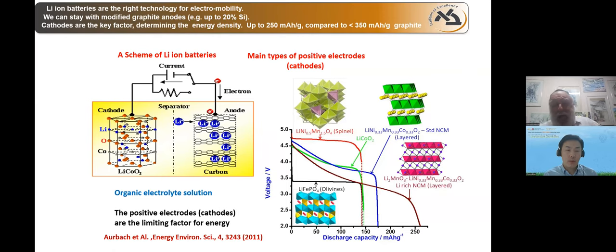And there are major structures that I can mention. We have the layer structure, we have the spinel structure, where we can reach a high voltage with this specific combination of nickel and manganese. We have the olivine structure, and these structures differ in the diffusion mechanism. In olivine it is in tunnels, 1D, one dimension, and in the layer compounds it is 2 dimensions, and in the spinel structure 3 dimension diffusion, which means that these materials are very fast. And I should mention this specific combination, the so-called lithium-rich NCM, where we have 2 phases. We have an inactive phase, and here we can obtain very high specific capacities that reach nearly the limit that can be obtained by a lithium transition metal oxide cathode.